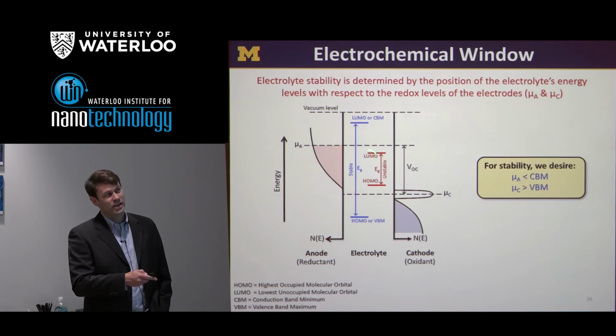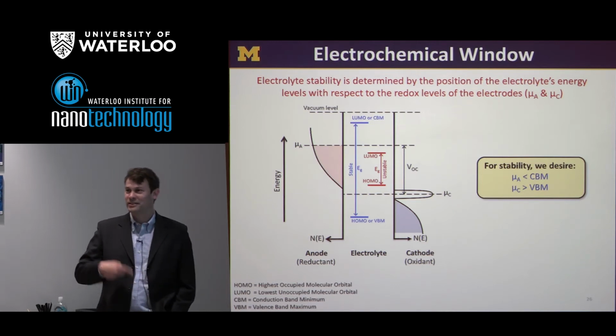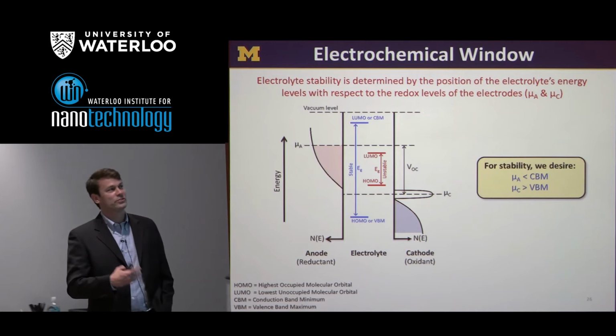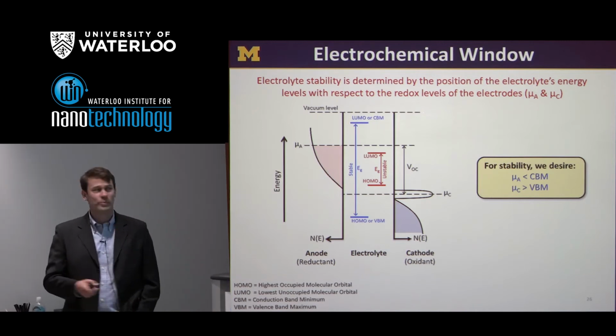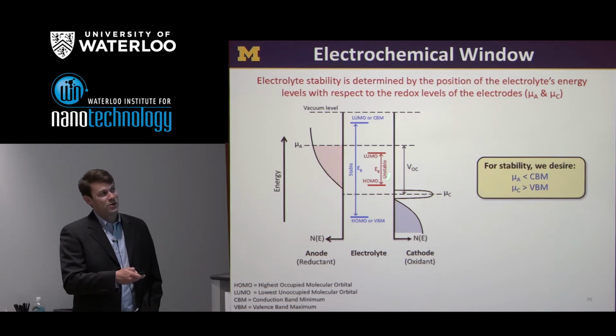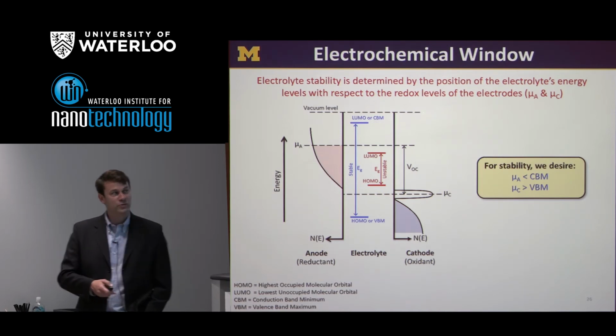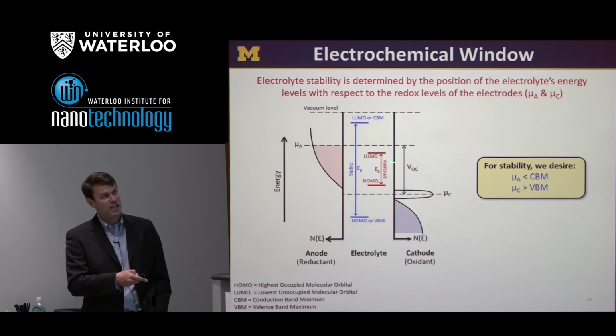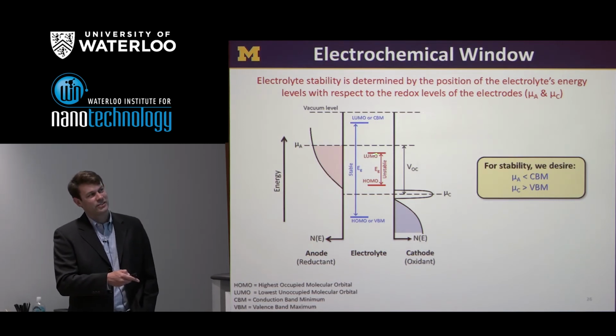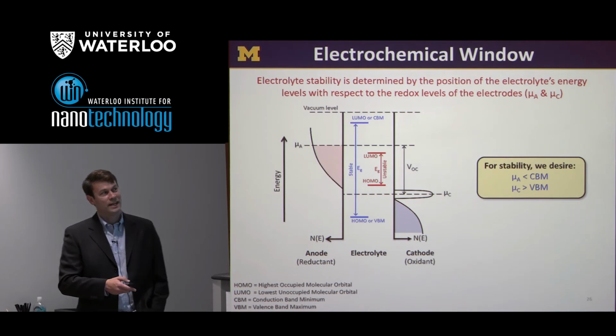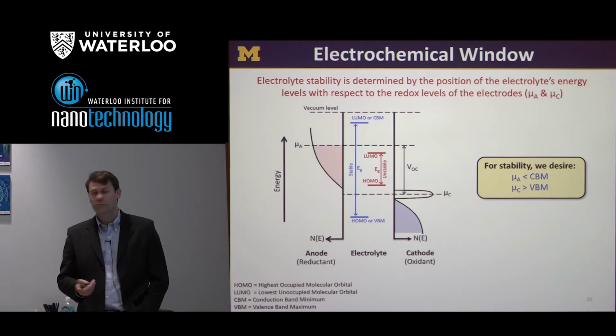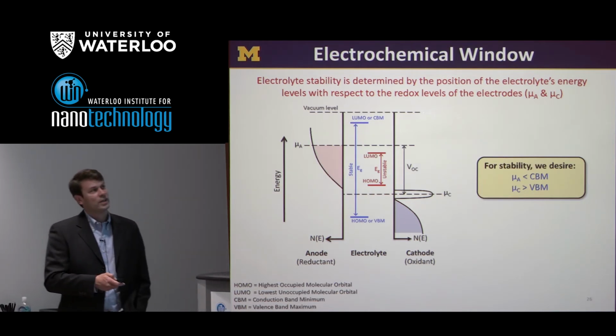That results in reduction of the electrolyte, and chemical fragments form. This is the process which leads up to SEI formation. So in that case, even though in, say, a liquid electrolyte for lithium-ion batteries, this LUMO tends to be reduced, the products that result from that reaction kinetically stabilize the electrolyte such that this level effectively moves up, and that SEI formation at some point stops.